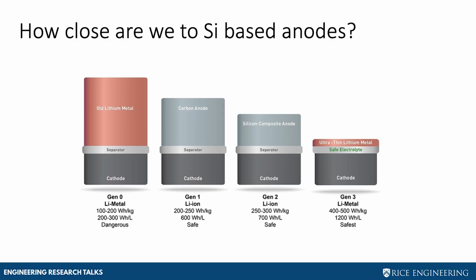So how close are we to silicon-based anodes? I like this plot because it's easy to see. This came from Whittingham's work, where he started with that generation 0 lithium-ion battery. You'd have this big lithium metal, which was very dangerous to operate, something you just couldn't see practical applications for. This is where we are now, that generation 1 lithium-ion battery. We have a carbon-based anode, separator, and a cathode. We are very close now to being able to realize that generation 2, those silicon composite anodes. And the future is going to be solid state, being able to use solid lithium metal. All of these are now possible.